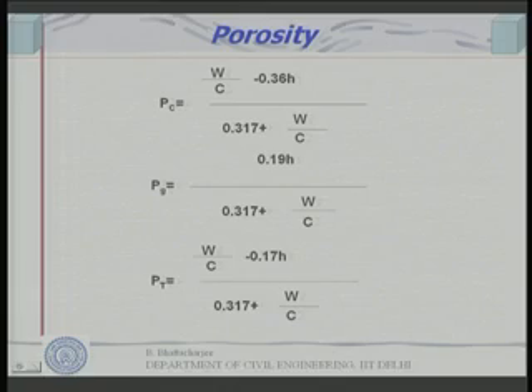So Pc denotes capillary porosity and it is given by W by C minus 0.36 H, where H is the degree of hydration, divided by 0.317 plus W by C. The 0.317 is related to the volume occupied by the original cement and water, 1 divided by 3.15 is 0.317, and W by C is the water to cement ratio. Similarly, gel porosity is given by 0.19 H divided by this, and total porosity is the sum of Pc plus Pg, which gives you W by C minus 0.17 H divided by 0.317 plus W by C. So this is the capillary porosity, this is the expression for gel porosity, and this is the expression for total porosity.